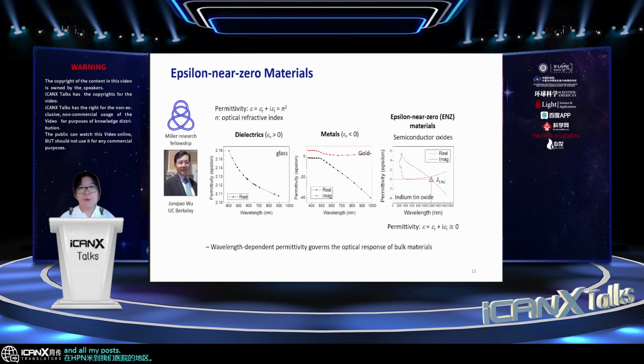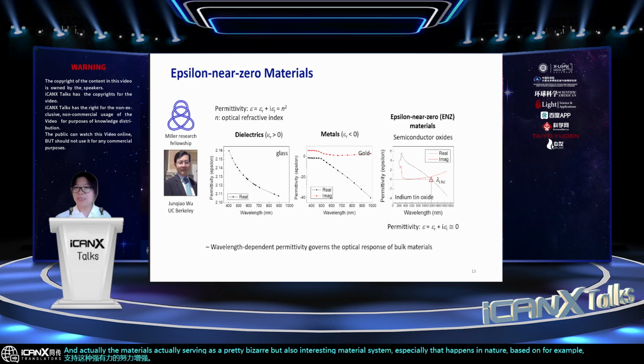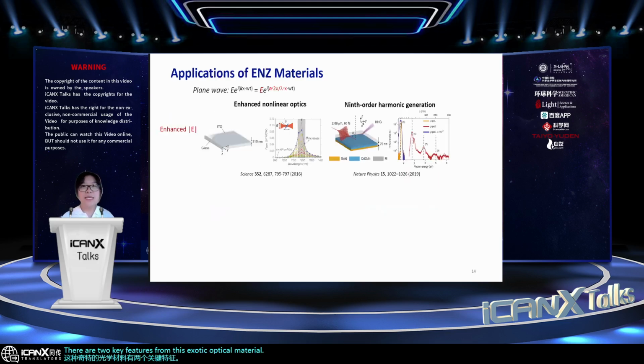And in my postdoc work, one question I asked is how to expand the material library beyond metals and dielectrics, to find an alternative system to support such strong near-field enhancement. Epsilon-near-zero materials actually serve as a pretty bizarre but also interesting material system, especially ones that happen in nature, for example, semiconductor oxide materials at the plasma resonance. There are two key features of this exotic optical material. One is the strongly enhanced optical fields at the interface with dielectrics. And in the past, it has contributed to enhanced nonlinear optics up to the 9th order.